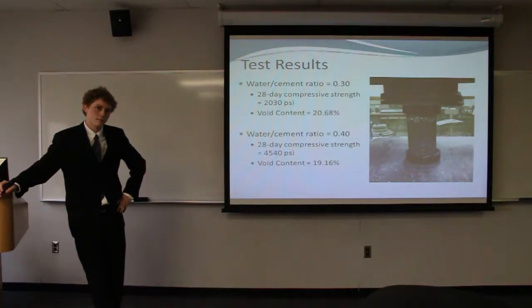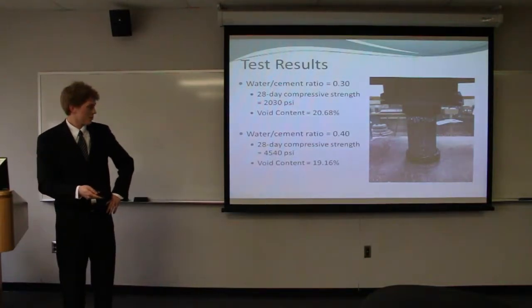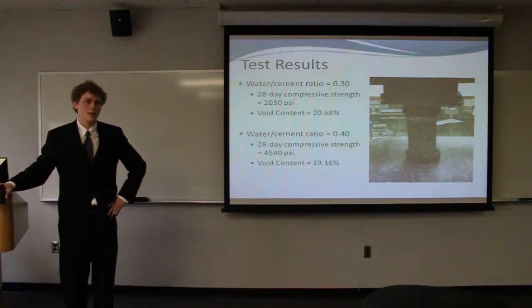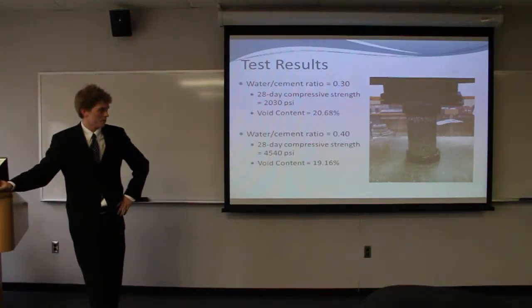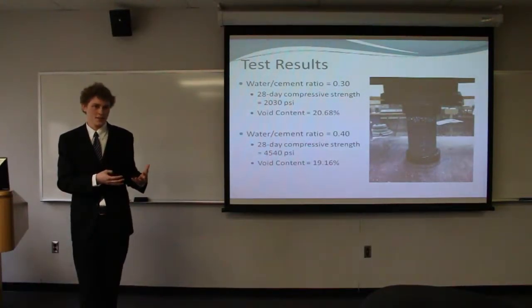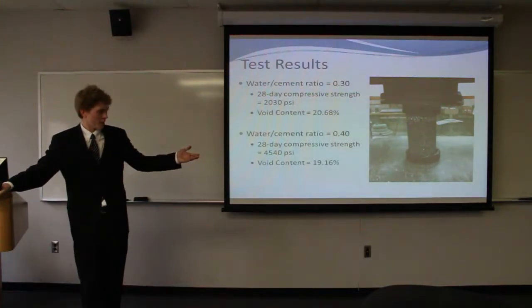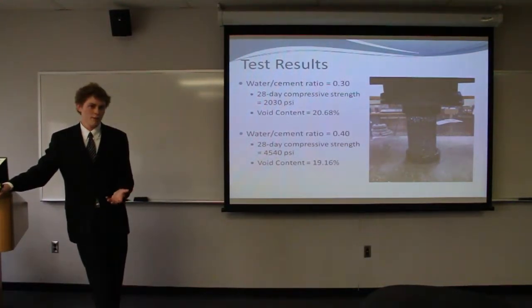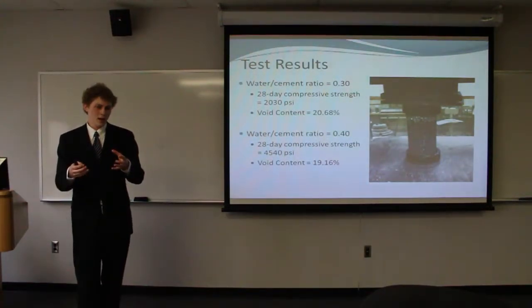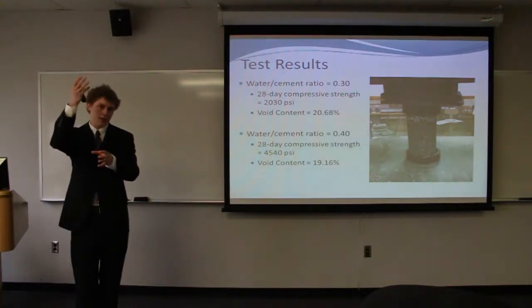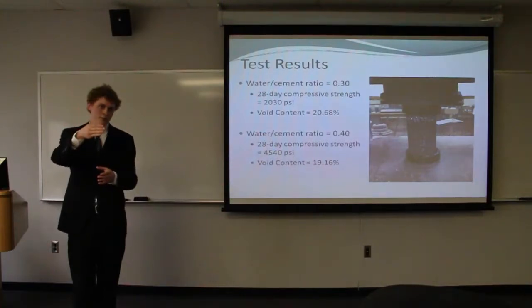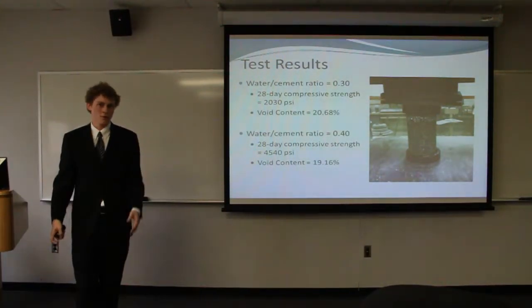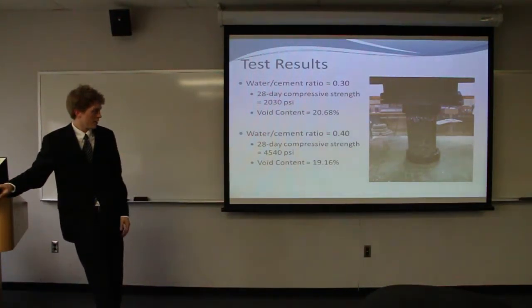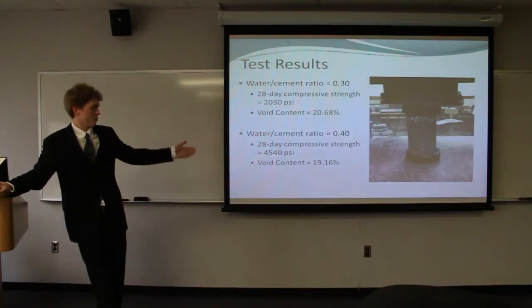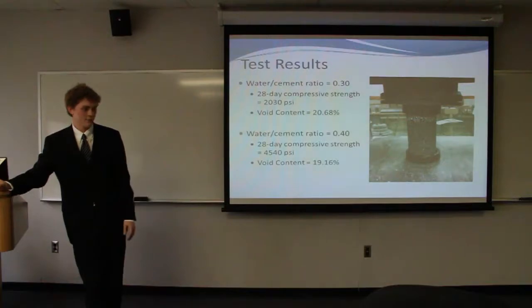Now the second one, did you test the hydraulic conductivity of the pervious concrete itself? We were going to, but when we would perform standardized tests on it, we would pour water on our pervious concrete samples, and it would immediately go through. So doing a falling head test on it would be hard, because it has to get clogged and backed up, and then you have to release the bottom valve for it to fall through. As soon as you release the bottom valve, it would just all go dumping right through it. Which isn't a bad thing, because since the void content is towards the higher end for pervious concrete, we have a high infiltration value.